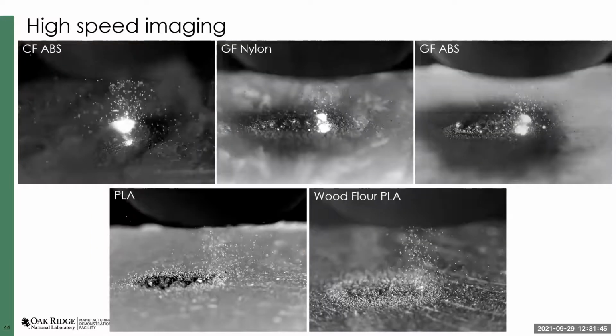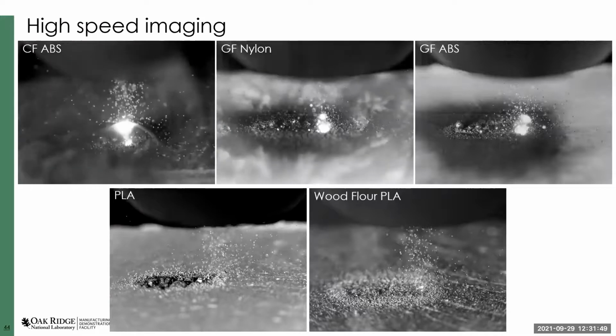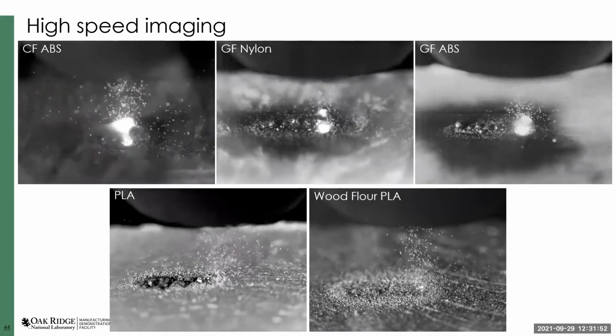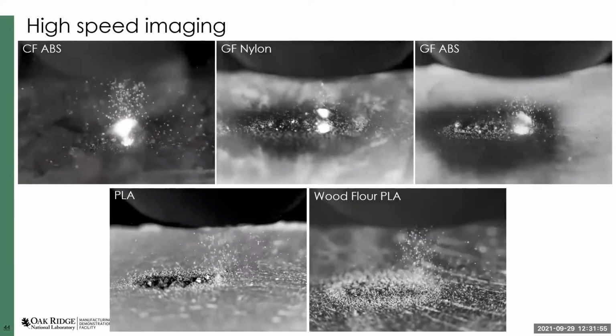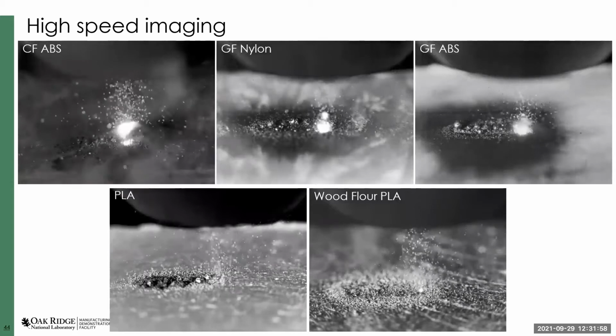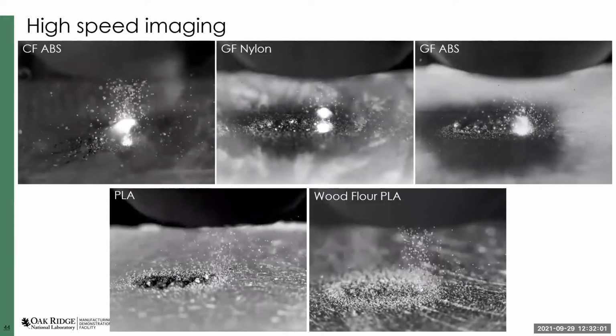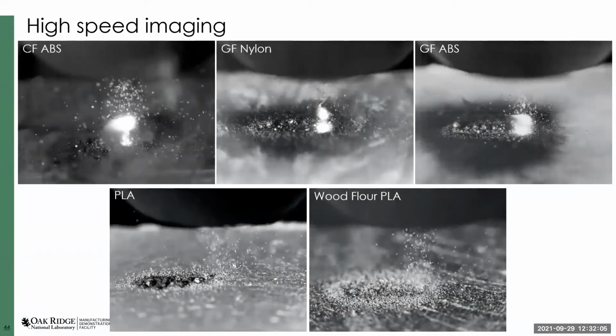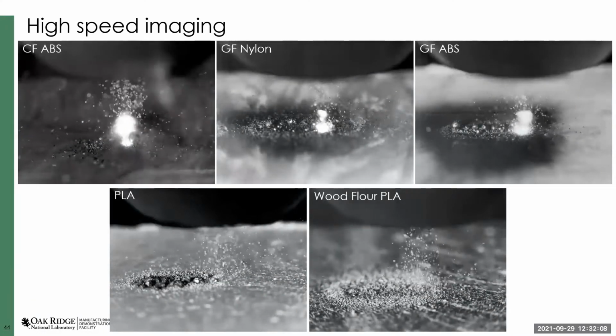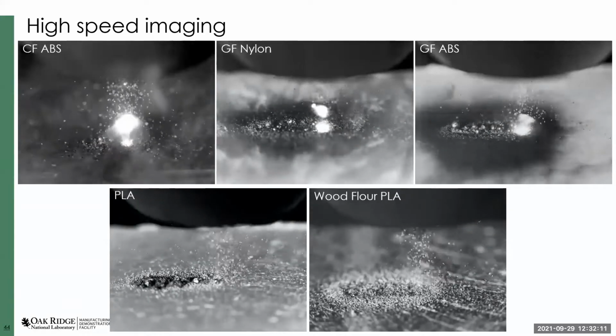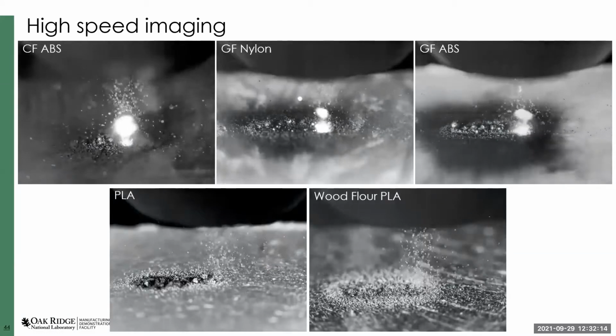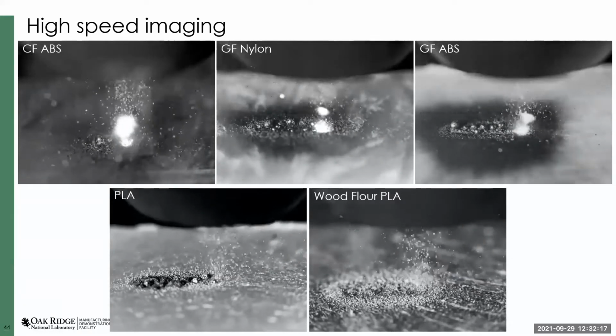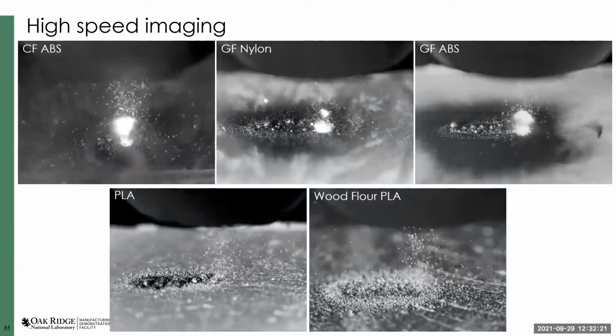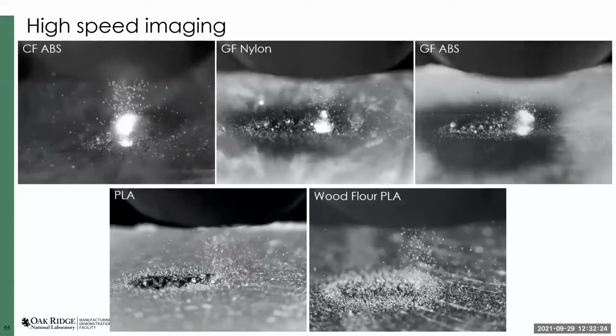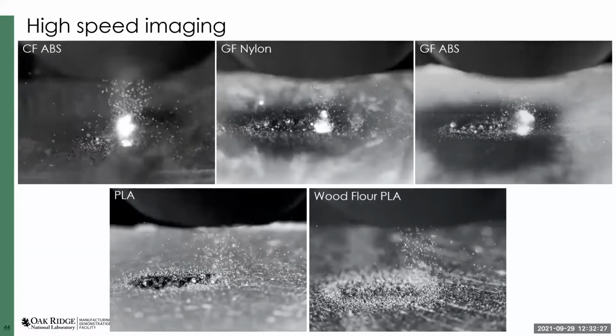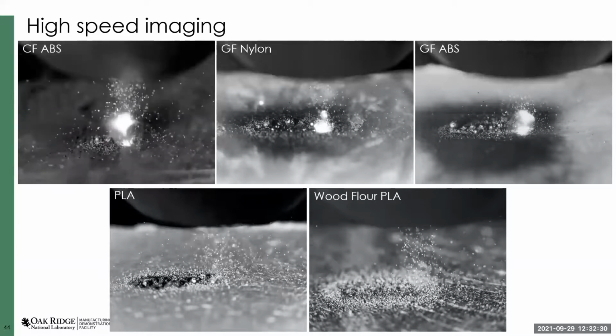And then I also did high-speed imaging of all of these materials. I'll just play them all at once so you can see them. And the high-speed images serve to further back up the hypothesis that with these filled polymers, the three polymers on top of this slide, you see degradation, so you see more significant flaring and more significant smoke as residue from this degradation, versus the two polymers on the bottom, which are not fiber filled, which have more of a melting of the polymer, embedding of that feedstock powder in the molten polymer, and then resolidification of the polymer.